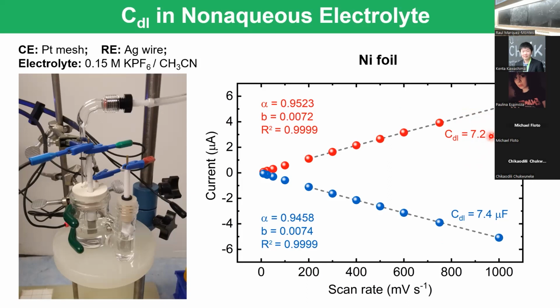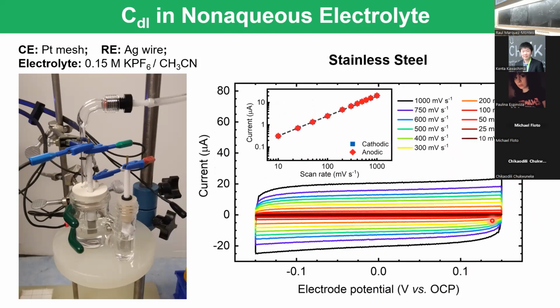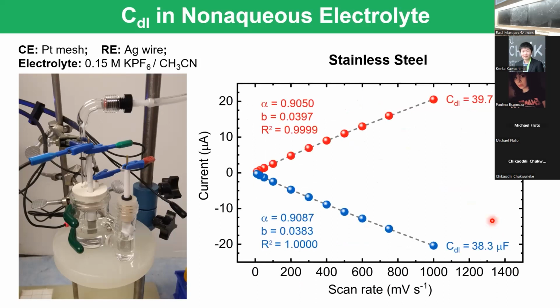Okay. Notice that it doesn't matter if we use the positive or negative values, the anodic or cathodic currents. We should get more or less the same value. Okay, this is stainless steel. We see the same behavior, an almost perfect rectangle. Also, we can use the same scan rate range. And again, we should see an alpha value like 0.9, which is expected. And notice that we can also get the double layer capacitance.